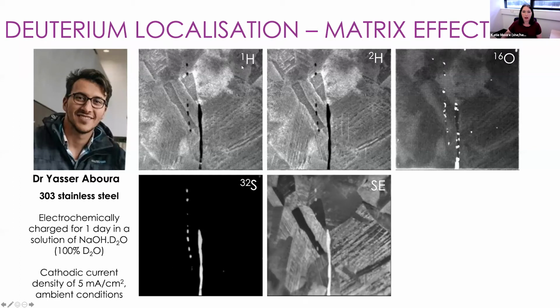Here we have our hydrogen map, our deuterium map, our oxygen map, and sulfur, which as expected shows a lot of sulfur in the manganese sulfides. At the same time as getting the ion images, we can also generate a secondary electron image in the NanoSIMS, which as you can see shows the microstructure of our alloys very clearly. When we look at our hydrogen and deuterium maps from this alloy, you can see up here, this region looks like it contains elevated levels of deuterium. But why should that particular grain have more deuterium than, say, this one here or this one here?